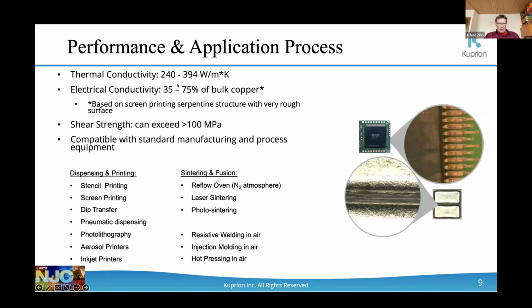So as kind of a top level view of the material, depending on the configuration, we have measured thermal conductivity as much as basically bulk copper. This is the latest data. Electrical conductivity is also very high. The reason for the spread is the way we have been measuring it so far, where we do screen printing. And because it's so thixotropic, you get a very rough trace line. And you have to assume some average thickness to calculate the conductivity, which is then, well, what do you apply when you have a very rough surface? So that's why I believe the electrical conductivity is very high, but these are the ranges we have measured with those printed lines. Shear strength is really good. It can exceed 100 megapascal depending on what size die you have.